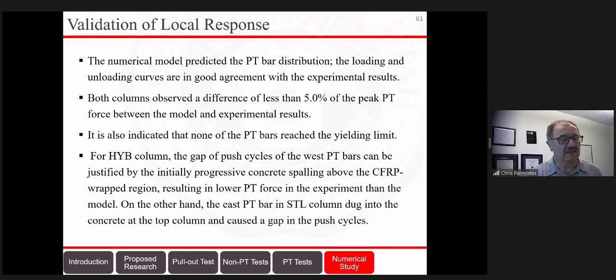Post-tensioning force was within 5% of the experiment. And we also saw in the model that none of the post-tensioning bars yielded. Okay, for the hybrid column, there was a gap in the push of the west bars. And this is justified because as we initially progressed damage and concrete spalling above the carbon fiber, we had a lower post-tensioning force in the experiment. But in the steel column, what we saw is that the post-tensioning at the top of the columns caused a little gap in the push cycle.